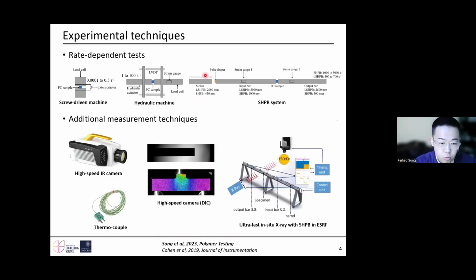The experimental techniques I used in the past 4 years are a screw-driven machine for quasi-static tests, a hydraulic machine for medium rate tests, and a split Hopkinson bar for high rate tests. I developed a long split Hopkinson bar to characterize this material at very large strain. Additional measurement techniques include the high-speed infrared camera, thermocouple, and high-speed camera with digital image correlation. Again, I went to the ESRF to perform ultra-fast in situ imaging with the split Hopkinson bar.